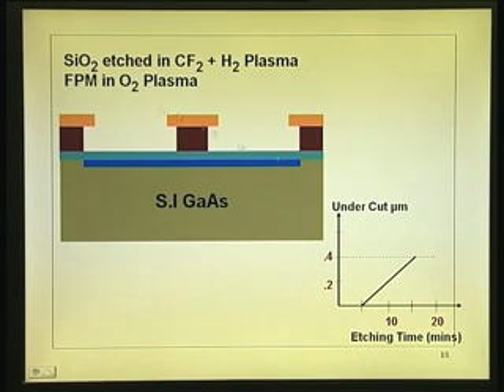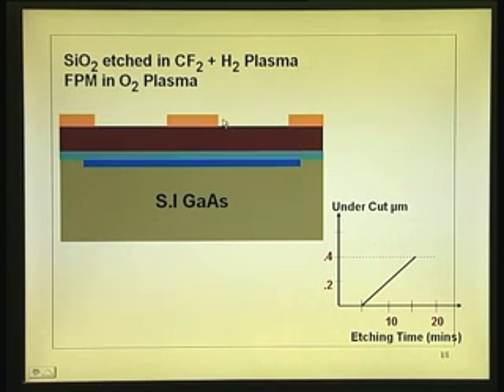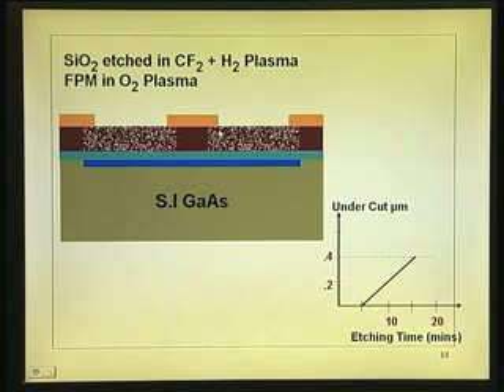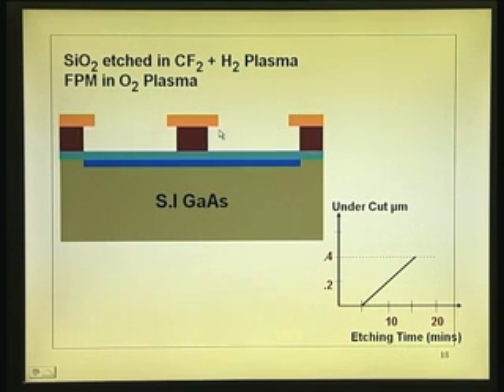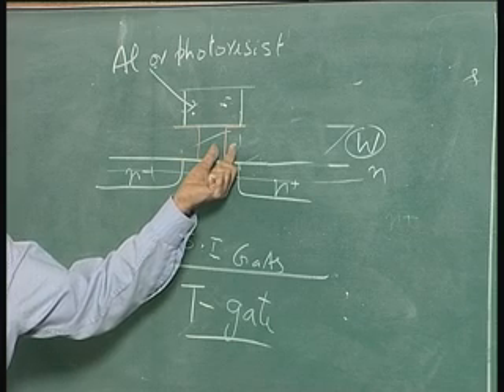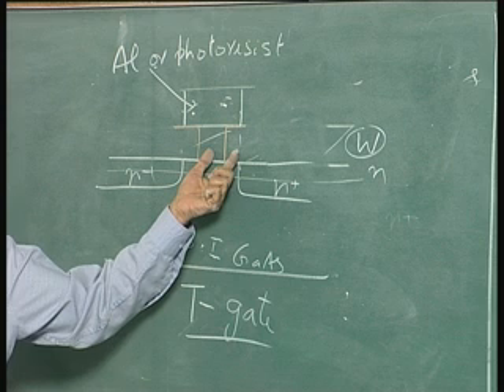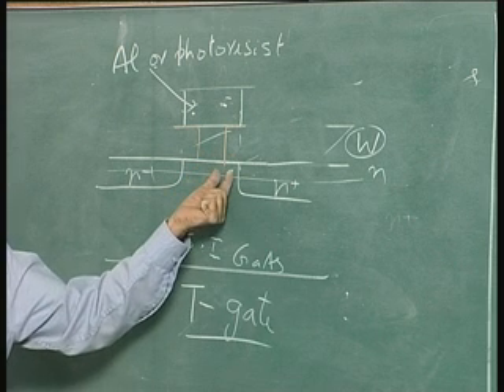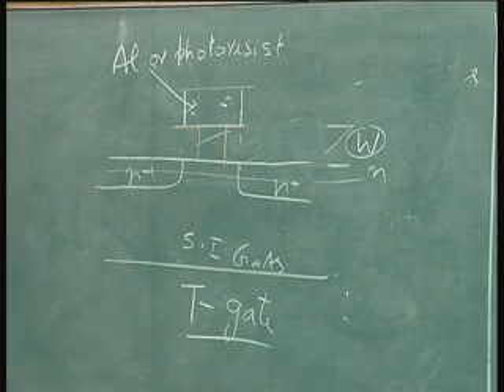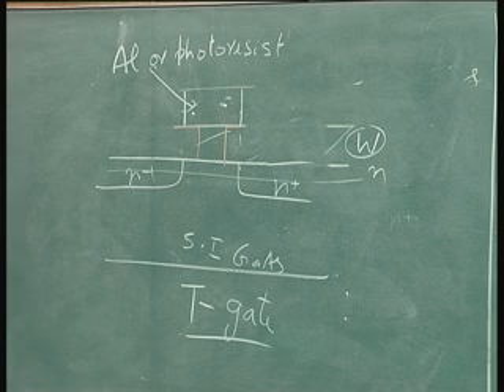Now, use this, go back to this, use this as a mask, keep on etching in the oxygen plasma, over etch it, you get the T structure, not in metal, silicon dioxide and photoresist. How much undercut is there? Precisely you can control by timing. This undercut, that undercut, here what is shown is metal, that will decide how much is the gap between the N plus layer and the gate. So, you can precisely control the undercut.